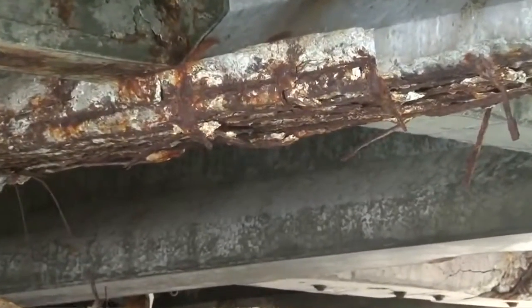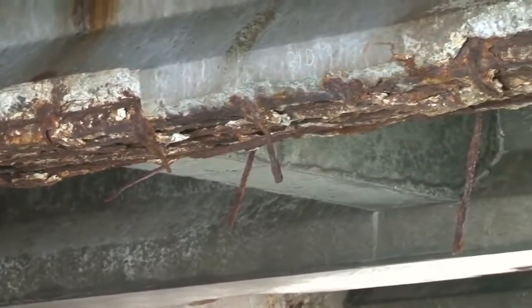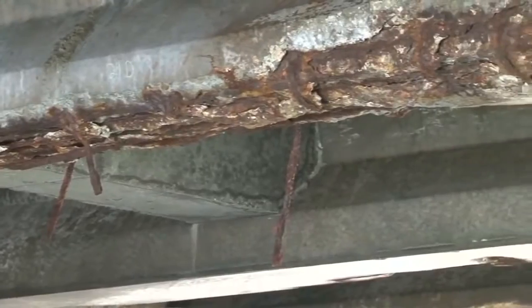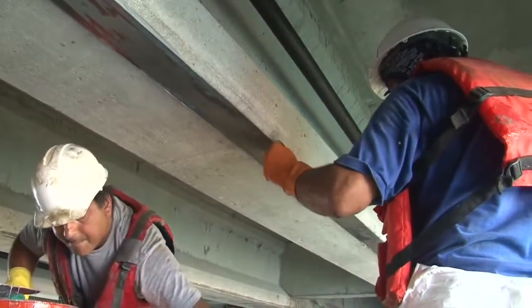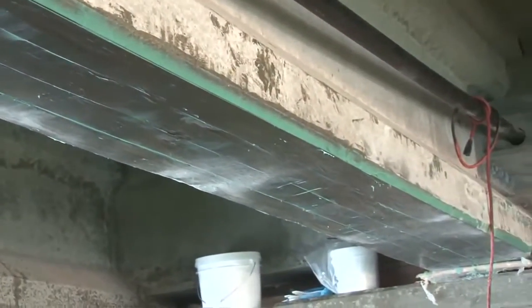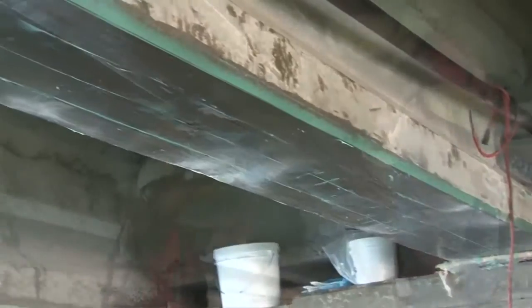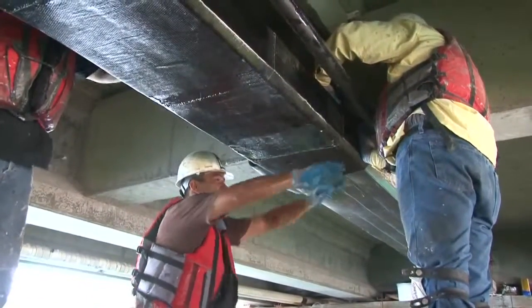Newport Harbor. Carbon Wrap determined that the solution for this project was to increase both the flexural and shear strength of the badly eroded concrete beams. For flexural strengthening, the company determined that the underside of the beams would be bonded with pre-cured rigid fiber resin laminate strips, and the entire beam would then be wrapped with the Carbon Wrap flexible fabric.